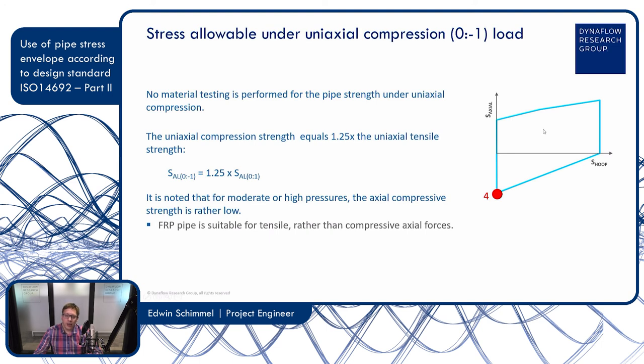And then if you have the other loads like thermal expansion or weight, we create additional bending stresses, and they result in a positive axial stress and a negative axial stress. The positive stress goes up here, and then already very soon we get to the top of the envelope. From this line with only pressure stress, if we go down, we see that we have a very large margin before we reach down to here. So this bottom part of the stress envelope for axial compressive stresses is small, but from purely pressure we are already far up in the stress envelope, so we have a lot of margin to the downside.